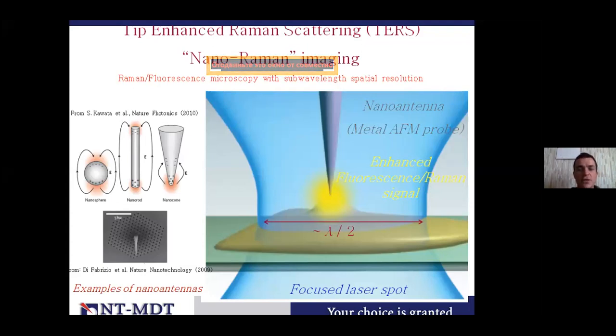So for this, we need to use the special probe, which is coated by gold or silver, and we need to put the light with the correct polarization on the tip. And finally, due to the plasmon resonance, we will get the dramatical increase of the intensity of the Raman signal, which is located only at the area under the tip. And since our tip is not few hundred of nanometer, but few tens of nanometer, then by this technique, we can increase the optical resolution from few hundred nanometer down to few tenths of nanometer. So down to 10 or 20 nanometers only, which is for optical resolution.